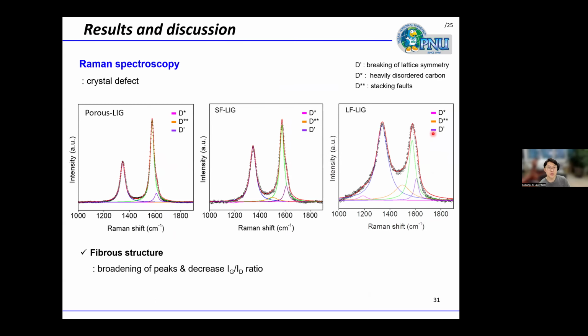In this case, not only the structure, but also the crystallinity and the composition of LIG are changed. Here, we refer to the conventional LIG as a porous LIG, and the LIG with the long fiber structure as a LFLIG. As shown in this Raman analysis, the fibrous LIG exhibits increased defect density, and the crystallite size gradually decreases as the structure becomes more fibrous.